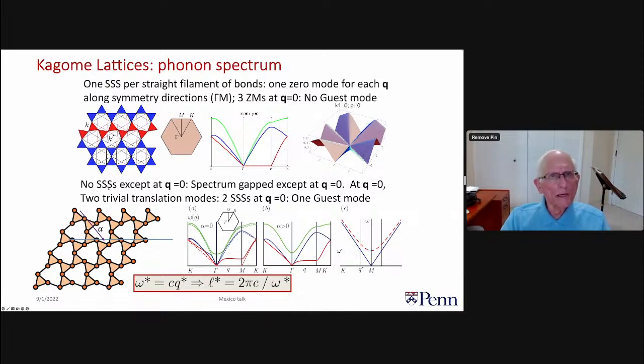Okay, so we've basically done this. Let's just go over it quickly again. This is the Kagome lattice, and notice, except for some region here where I've shown what the zero energy distortion is, it has straight lines of bonds that go all the way across the sample, and you can think of this as being wrapped on a torus. That means that this end of the straight line of bonds is connected to that end. So you can put this under stress, say, imagine blowing up the torus, stretching out the bonds, and you can have stress in every one of these bonds going along there without having stress in the other ones.